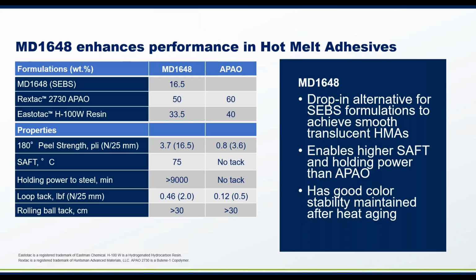So MD1648 can enhance the performance in hot melt adhesives. The table here shows two APAO formulations, one with MD1648 and one without. And as you can see, an improved performance is observed by adding the MD1648 polymer, especially enabling higher shear adhesion failure temperature, and holding power. And in addition, MD1648 offers a good color stability after heat aging.